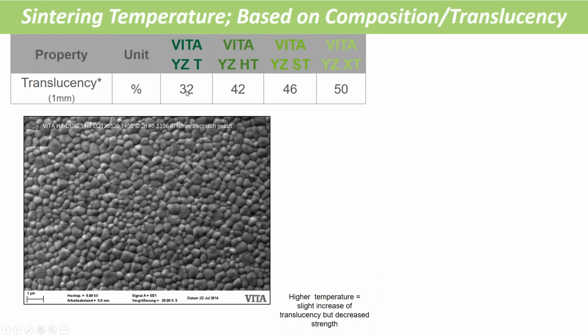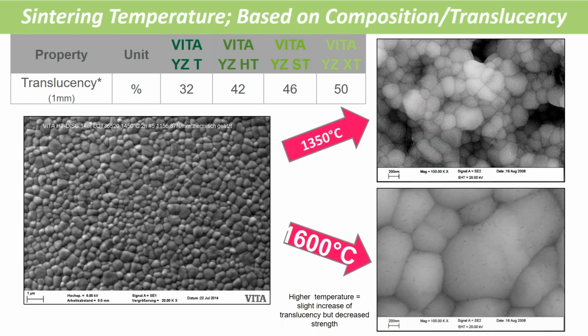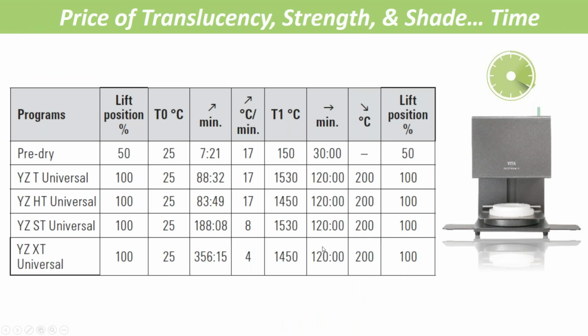So our zirconia, depending on the type and the translucency level, we sinter differently because we want to maximize the crystal growth. Certain compositions of zirconia require a certain temperature to optimize the grain size and to ensure that the grain boundaries are sufficient to allow the light penetration and diffraction of light so that it looks translucent. So if you go too high on any particular material, it does give you a slight increase of translucency, but the strength is compromised. It's decreased. So be careful when you think all zirconia should be sintered at the same temperature. They're not.